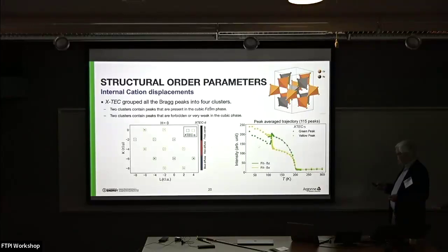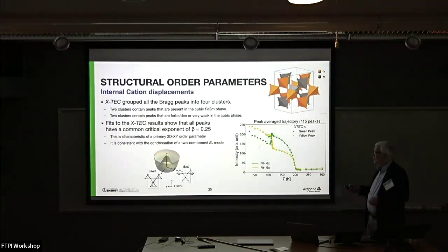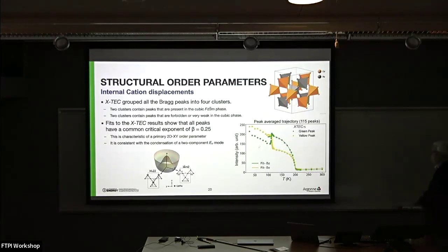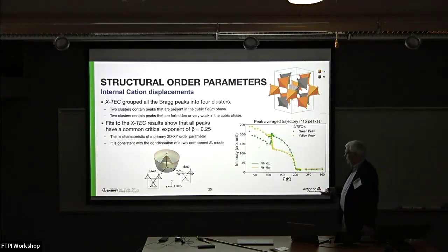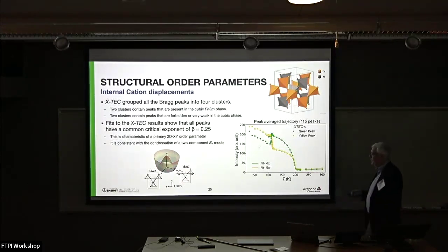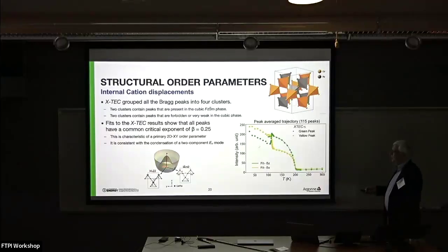But the critical exponent of both of them, going from the distortion, is 0.25, which is interesting because it's a 2D XY exponent. And that's what you would expect for the condensation of a two-component Eu mode. Basically, there are two possible ground states, I-4m2 and I4122, and they're nearly degenerate, so you form this kind of Mexican hat potential, and so you're going to get very strong fluctuations within that, which will lead to an exponent just like this. But it definitely is the primary order parameter, so we're in disagreement with the SHG results on that.